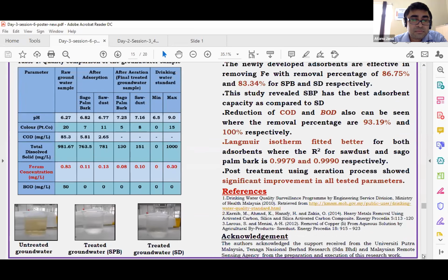So the drinking water standard set in Malaysia is about 0.3. This has been proven by applying this technique. We can remove ferrum and also some compounds of color, chemical oxygen demand. More than 70% of chemical oxygen demand has been removed, as well as biochemical oxygen demand. By removing these particles, especially ferrum, we managed to remove total dissolved solids as well.